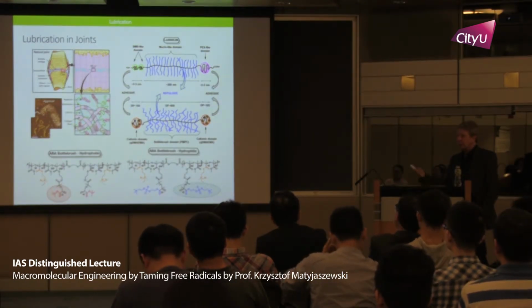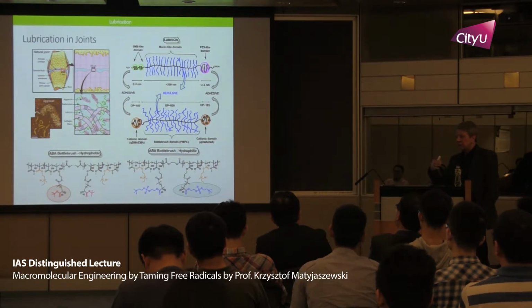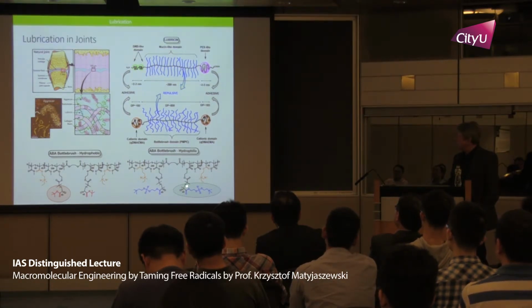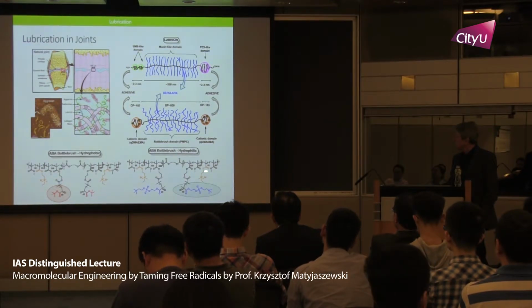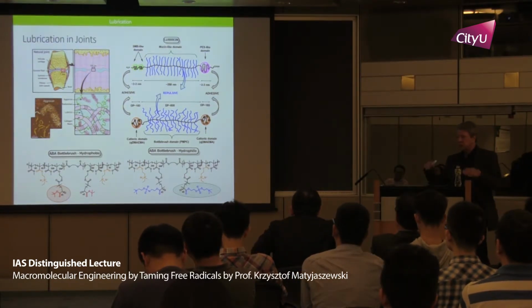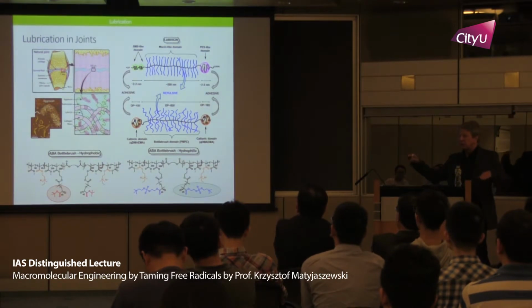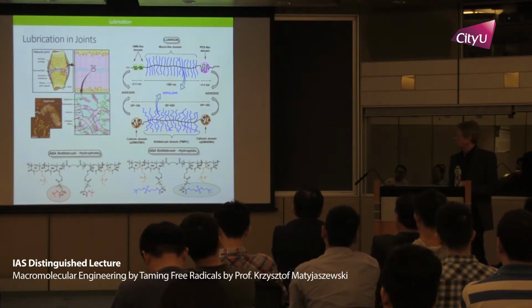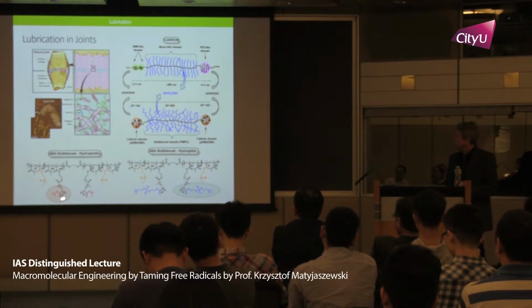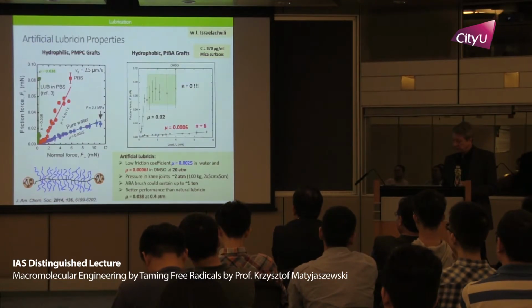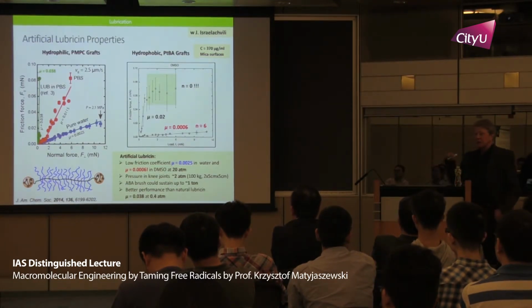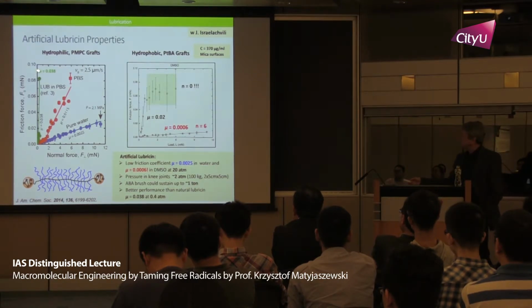acid. And we wanted to make a synthetic model of this lubricant by using methacrylate with phosphorylcholine functionality, very biocompatible, and also quaternary ammonium groups, because this was done on a mica surface, so it can connect to mica surface. And also another example is for the hydrophobic brush as well.